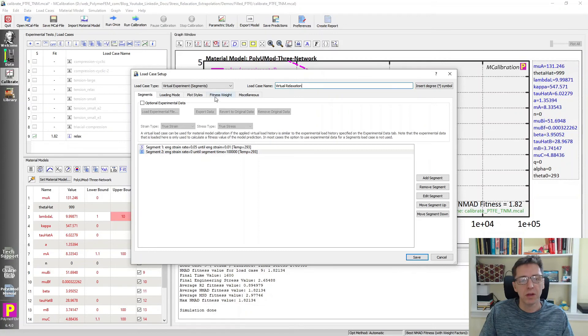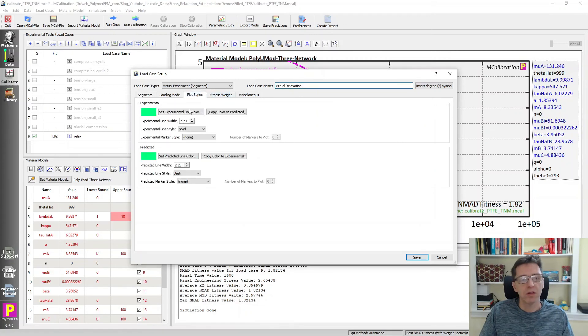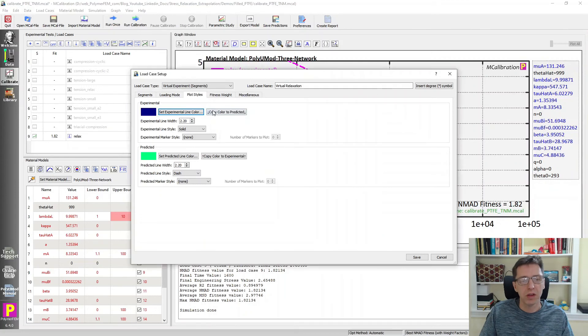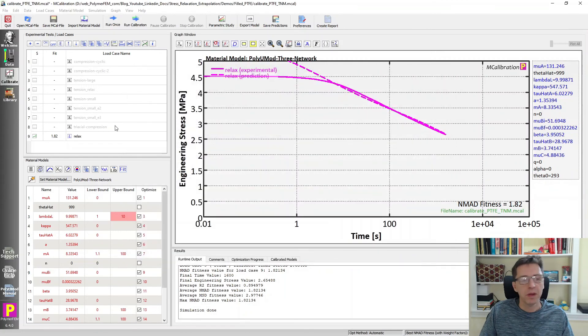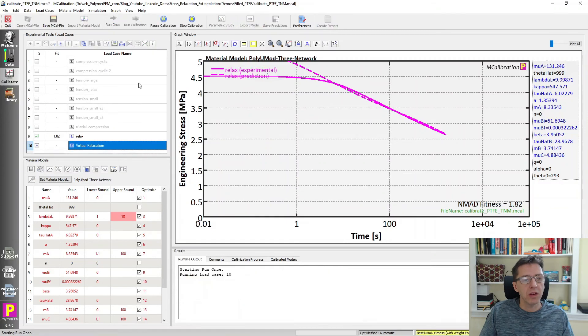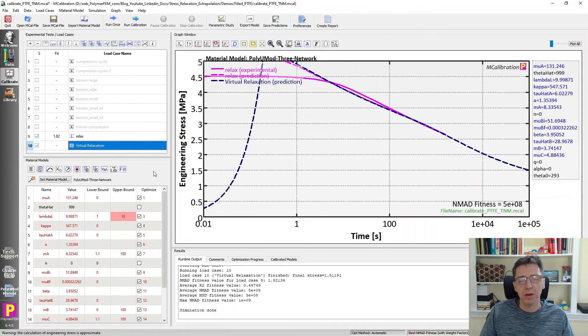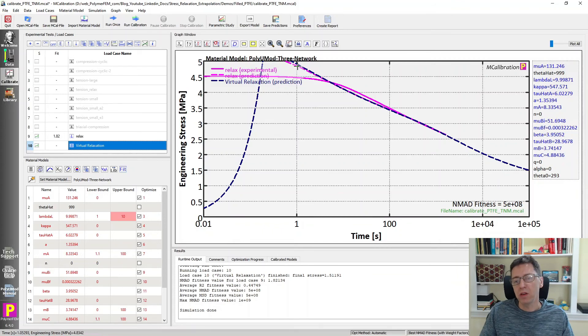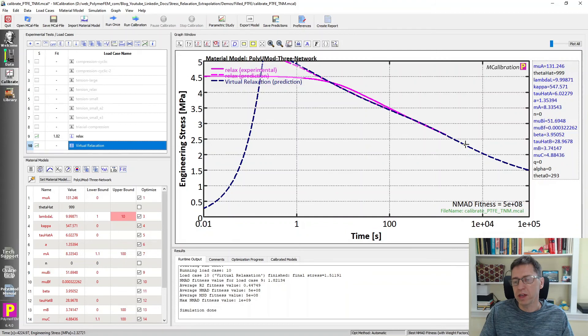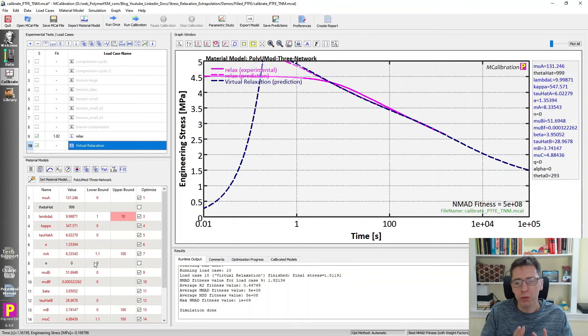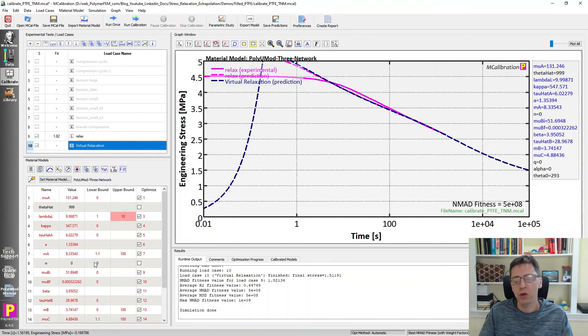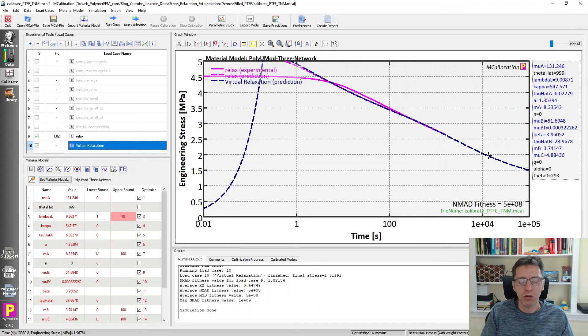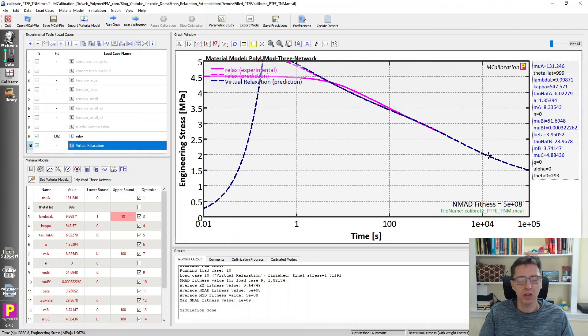Let's see if we can change the color to something easier to see. I'm going to run this load case here. We'll see that we have this initial load up portion of the three-network model, but we can also see that the three-network model continues to relax, just like we would expect the stress relaxation to occur. So in this case, the three-network model is a robust enough model. The equations have been formulated in such a way that the rate of relaxation is following this kind of response that's typically what one sees experimentally.